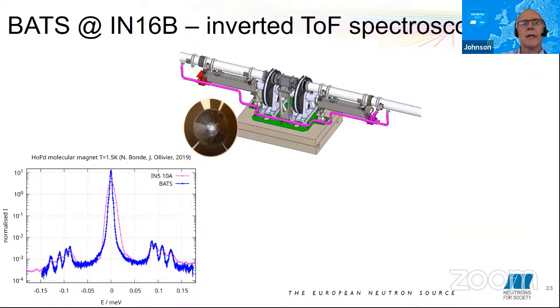And this has been increased recently through this BATS upgrade, where we use choppers on the incident beam to essentially increase the possible energy transfer. And there's a sophisticated pair of choppers which have different size openings, which allow the energy resolution and therefore the flux to be tuned. So the data shown in the bottom left shows a comparison between IN5 and BATS. So we get much better resolution from BATS using the backscattering technique, but actually a much wider Q range as well, and that's very important.